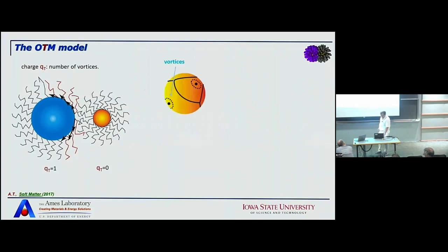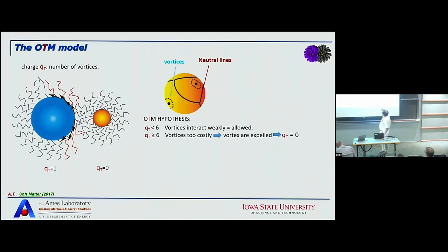We can discuss. And then you can have many situations where you have different vortices distributed along the sphere. For those of you that like topology, there is no topological restriction here about how many vortices you can have, because these are three-dimensional order parameters. It's not a two-dimensional order parameter on the sphere. So the bottom line is that the idea was that vortices, these splayed configurations, create domain walls. They interact very strongly, and there is a maximum number of these that you can have on a sphere, energetically, not topologically, just pure energy. And the other thing is that once you have one of these splayed configurations, you can also maximize the packing fraction, because then you can break the hard sphere description, but there is also a maximum of the packing fraction that you can attain.